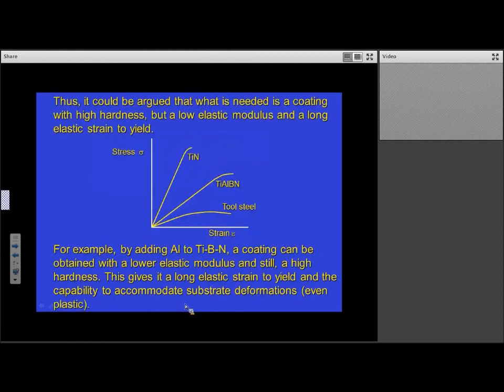So if you take a very simplistic view of this, and this is just representational, it's not an exact scale diagram, if you had a coating which happened to be slightly softer than another coating, and had a lower elastic modulus, then it could have a longer elastic strain to yield and therefore would protect the underlying material for longer, at a higher level of strain. So in this particular representation, this coating could protect this material even when this material is strained beyond its yield point, which obviously would be an excellent property for a coating to have, if it continues to provide protection to the surface even when the underlying surface has yielded.